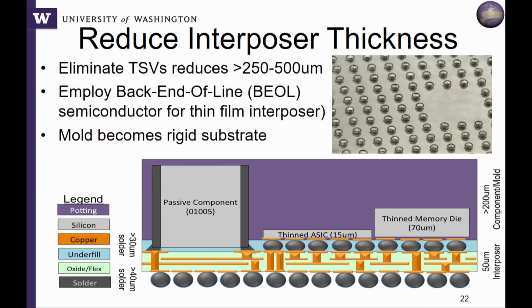We're able to take a substantial portion, about 0.5 millimeter of that thickness, by removing the handle completely and just using the metal and dielectric that we put on top of the wafer as the interconnect between the chips. So we're able to get things down to sub 15 microns or so. In fact, we've done things as low as just about 15 microns as far as the interconnect goes.